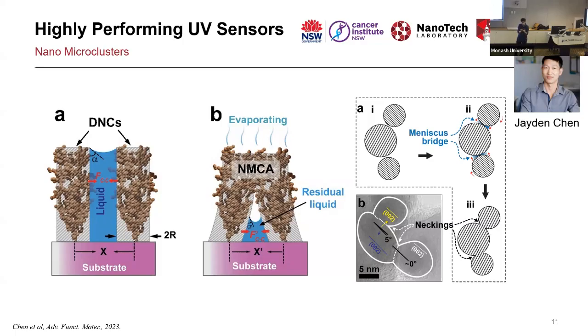But the other one is, again, this is what I hypothesize. I think that the atoms in the structure, because of the condensation of the solvent, receive a little bit of freedom to move around. With different vapors, it didn't work with all of them. Like in zinc oxide, it worked beautifully with acetic acid, and I think it's because zinc has a little bit of solubility. But if we hold it above the kettle when it's boiling, the water didn't work. It looked exactly the same as before.